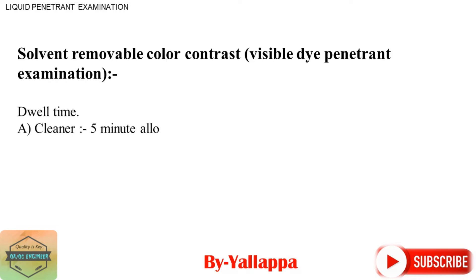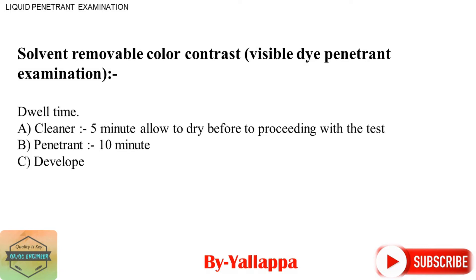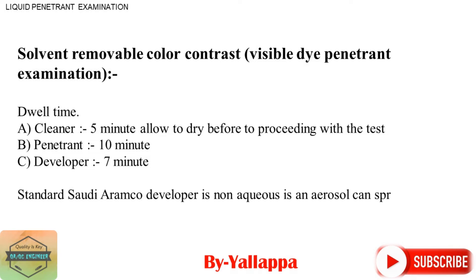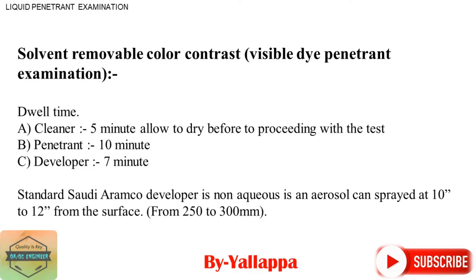Dwell Times: A. Cleaner — 5 minutes, allow to dry before proceeding with the test. B. Penetrant — 10 minutes. C. Developer — 7 minutes. Standard Saudi Aramco Developer is non-aqueous, supplied as an aerosol can; spray it at 10 to 12 inches (250 to 300 millimeters) from the surface.